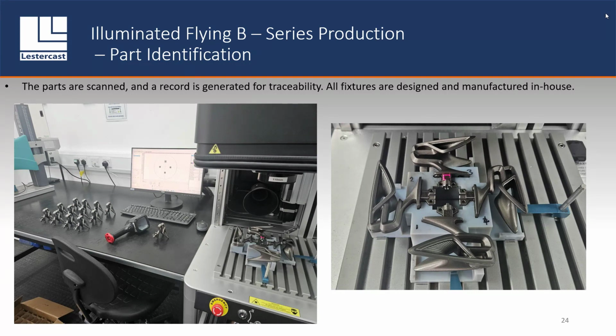So we have an operator that basically sits here and sets these 4 parts up, goes away, comes back 10 minutes later, and this is done. So the data matrix is done purposely quite deep, because it needs to survive quite a few aggressive processes: shot blasting, core leaching, polishing, etc., and needs to stay visible for the entire life cycle of the part. So it's a really good addition, and something that is quite crucial to this part, and the same with the plinth.